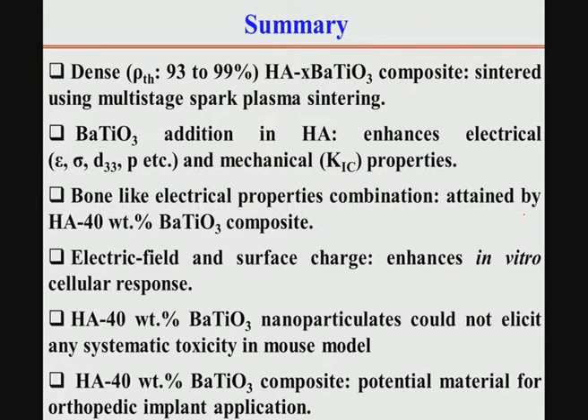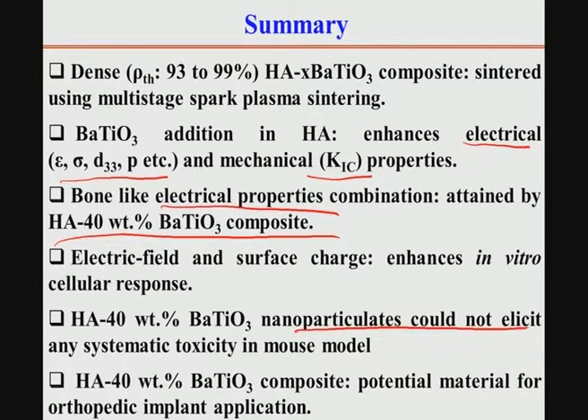So, in summary, barium titanate addition in hydroxyapatite moderately enhances the electrical properties, that is the dielectric constant, piezoelectric strain coefficient, as well as the conductivity, and to a moderate extent it increases the fracture toughness, like 0.86 or 0.9 MPa square root meter. These bone-like electrical properties were particularly obtained in the case of the hydroxyapatite 40% barium titanate composite, and these nanoparticles did not elicit any systemic toxicity in the mouse model, and therefore, these materials can potentially be used for orthopedic implant applications.